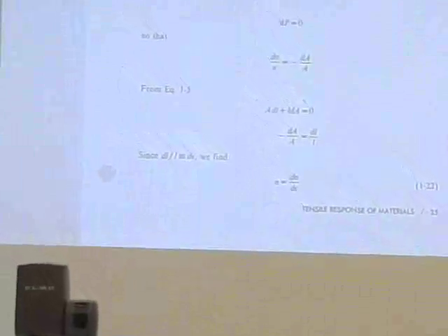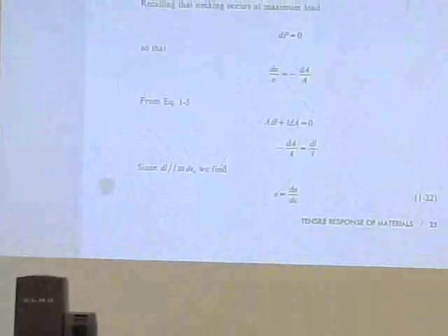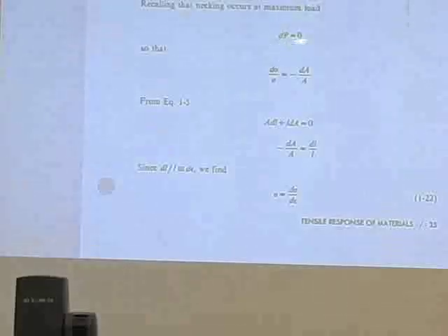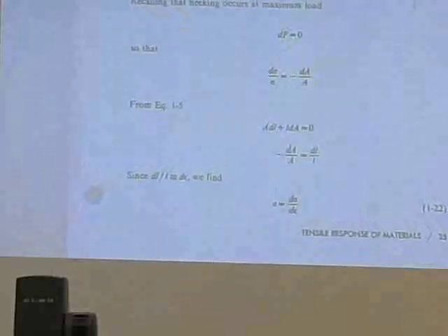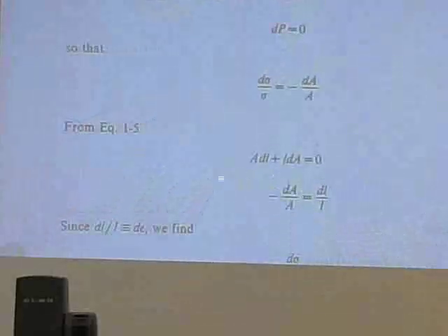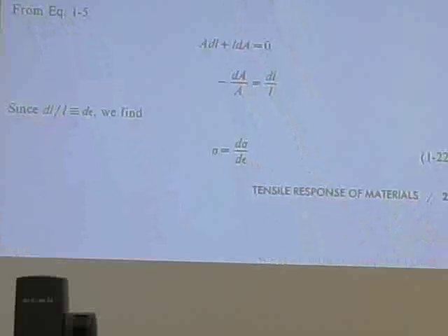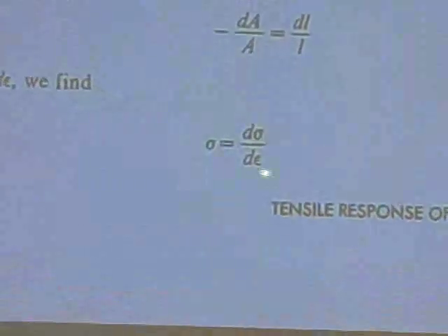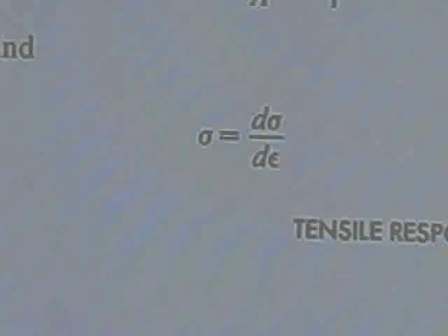That same incremental dr. Anyway, so load is equal to stress times area. That's pretty simple. You take the complete derivative of that and you set dP equal to 0, and you get d sigma over sigma is equal to minus dA over A. You then write down the dA over A in terms of L, and say that dL over L is d epsilon, which is your strain, and you get that the stress is equal to the derivative of stress with respect to strain.